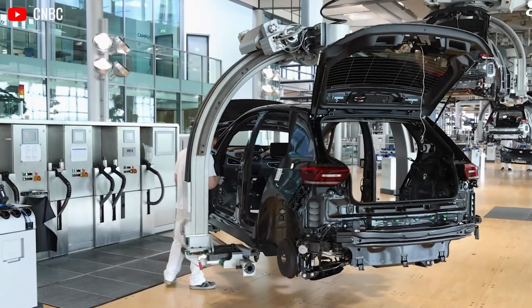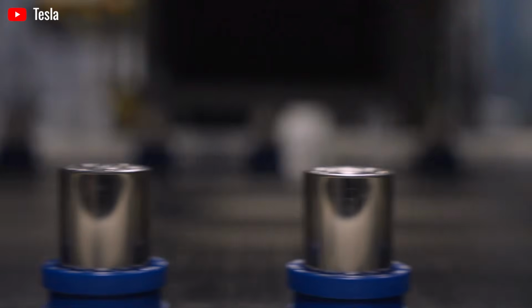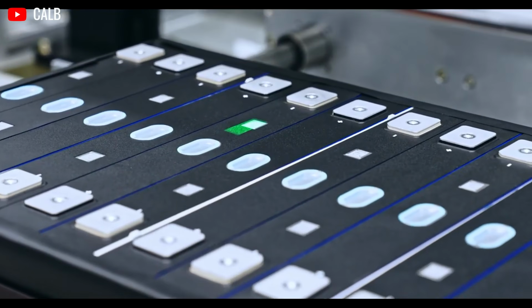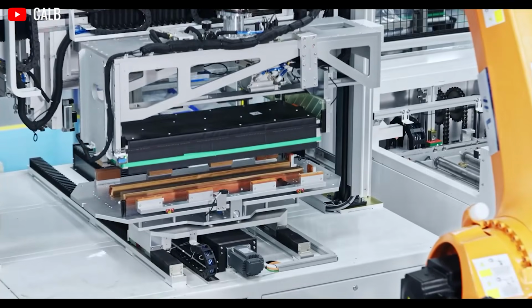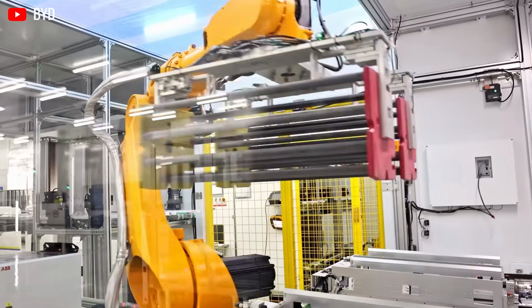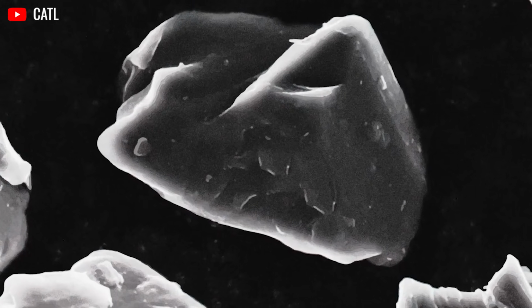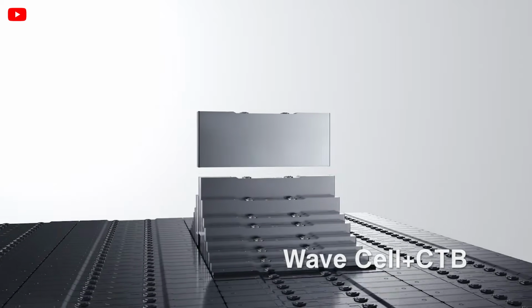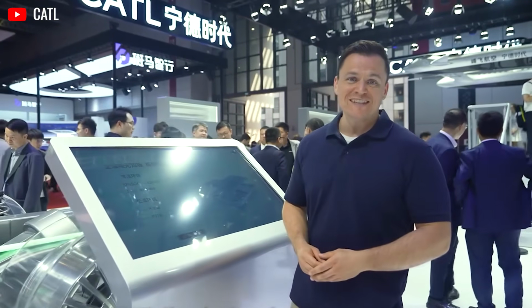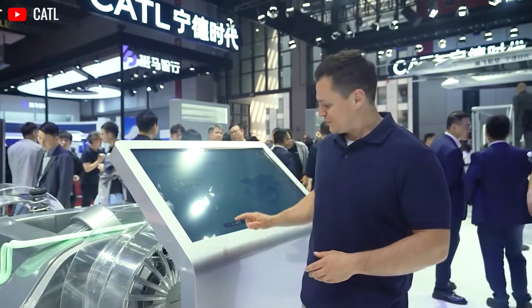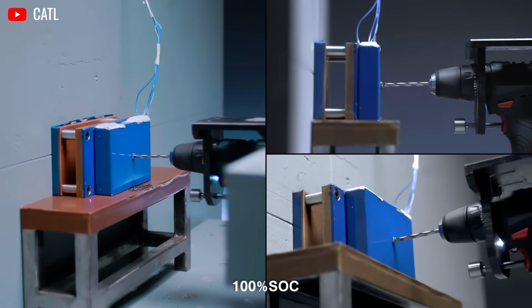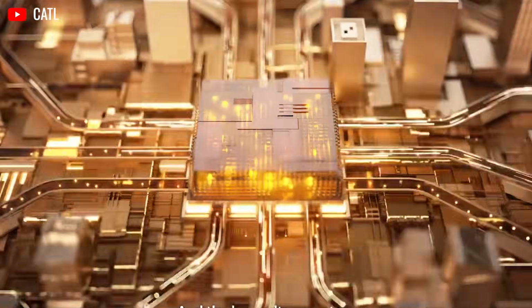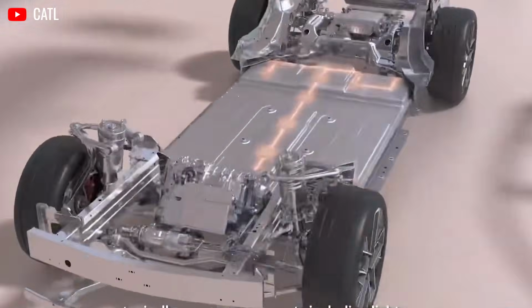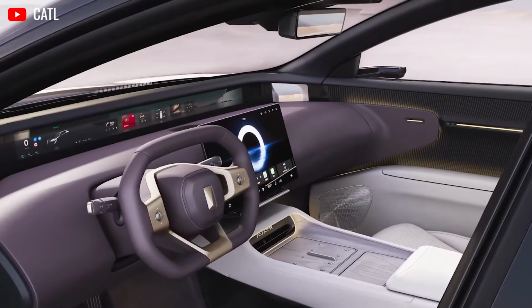In laboratory coin cells, clever binders and nanostructuring can partially tame this expansion, but in real automotive-sized cells, repeated swelling and contraction pulverize the electrode structure from the inside. Cracks form, electrical contact is lost, and fresh surfaces are exposed to the electrolyte, accelerating unwanted side reactions. The cruel irony is that the very materials we need to reach 400 watt-hour per kilogram are the ones that mechanically destroy themselves the fastest. If material instability were the only problem, engineers might brute force their way through it with clever designs.